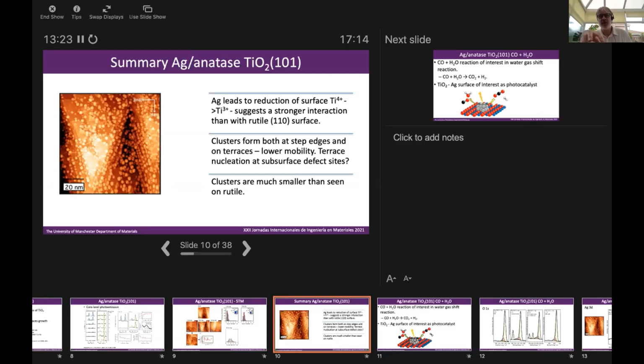And we wonder, therefore, whether this terrace nucleation occurs at subsurface defect sites. Unfortunately, with this STM, we weren't able to get atomic resolution, which would allow us to identify these subsurface defects and see if this is where the clusters were growing on that surface.